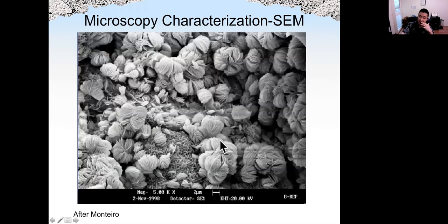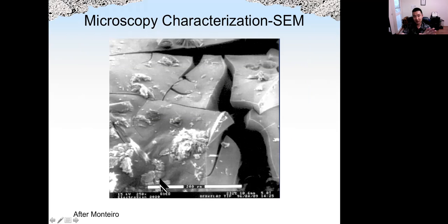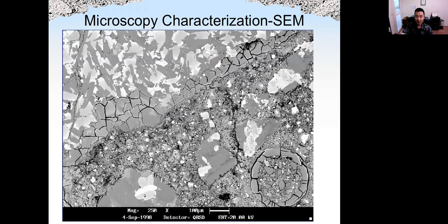Okay, so seen from the scanning electron microscope, we see ASR gel looks like a cotton flower. The scale here is 2 micrometers, so very, very small scale. In 200 micrometer scale, we see the gel looks like this. Here is 100 micrometer, which is 0.1 millimeter. We see the cracking also in the ITZ, so between the aggregate and the cement paste. And the crack may pass through the cement paste and also through the aggregate.